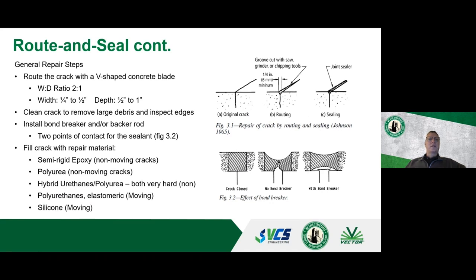I won't go through every single step, but there is a very important aspect of doing the route and seal, and that is the width to depth ratio when you go to do a repair, because the repair materials that are typically used in this, and you'll have to reference back, are specific. If you have a 1-inch crack, then you've got to make sure that your width and your depth go together at a 2 to 1. So if you think, okay, it's really deep, but I'm going to keep this pretty narrow, that's not going to work out very well.